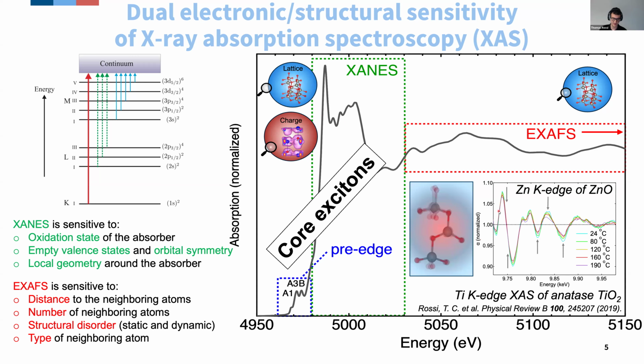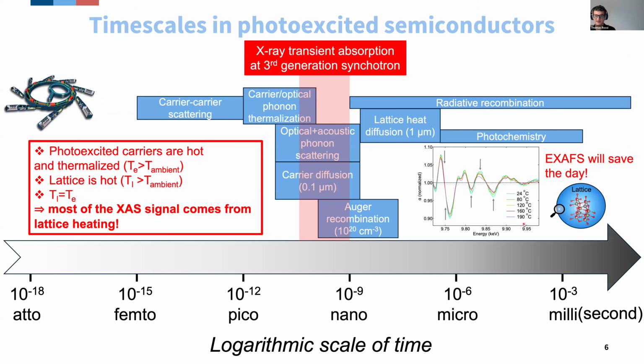And typically, the kind of dynamics we are going to look at in the EXAFS today is lattice heating. I'm going to focus on experiments that are done at the synchrotron, and the time resolution of our experiments is typically of the order of several hundreds of picoseconds. And on these time scales, what you see in photoexcited semiconductors is a lot of heat in the lattice that tends to give a very strong signal in the EXAFS. And this is important because at third generation synchrotrons, where we do our experiments, the time resolution we have is typically around here on a logarithmic arrow of time. So we are in the range of several hundreds of picoseconds.